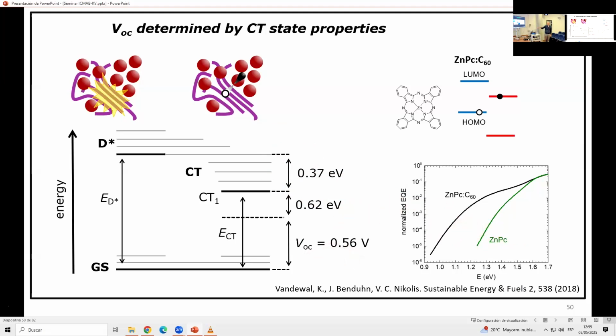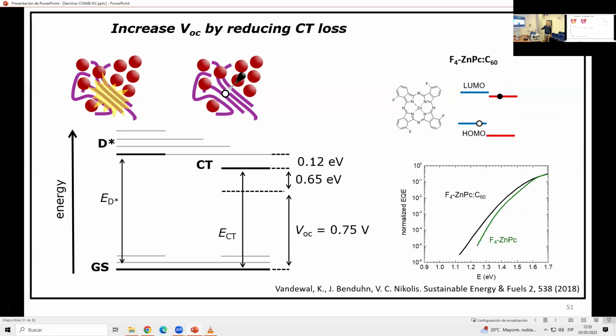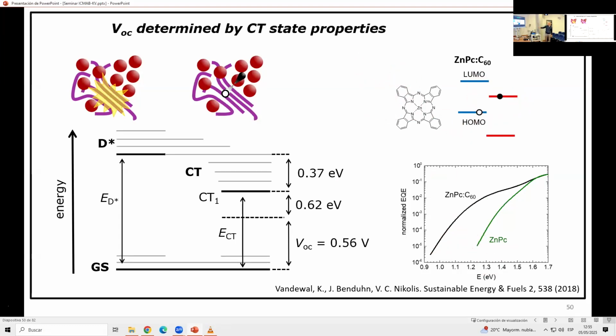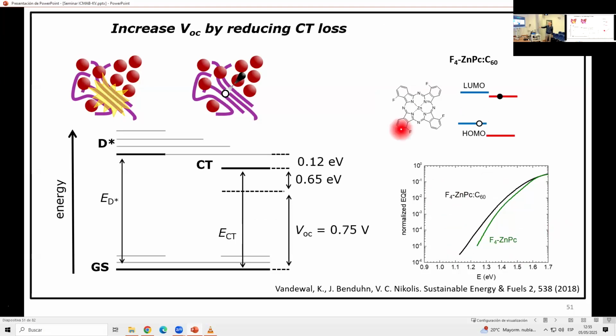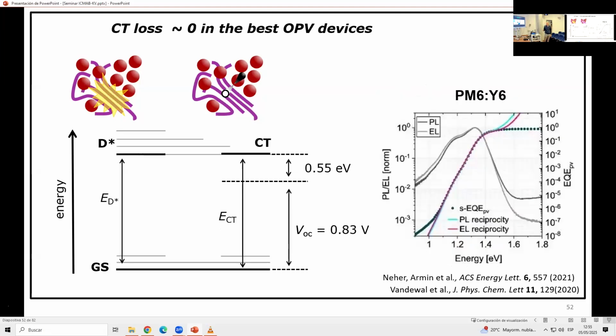So then, if you fluorinate zinc PC, oh, too fast. If you fluorinate it, it's known you shift the HOMO and the LUMO down, so you do expect higher CT state energy, and that's also what you saw if you look here. If you use the fluorinated version, you really shift this interfacial absorption to the blue, and you indeed have higher voltage because you have less losses in this CT process. And then you could say, the next one, you completely make it disappear. Will the solar cell still work? And it really is the case like this.